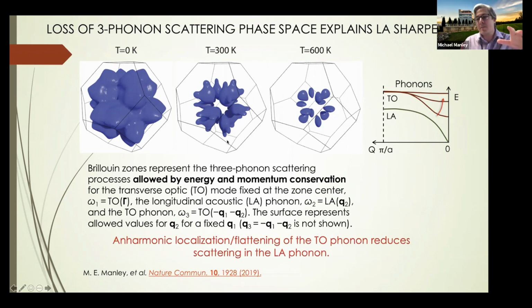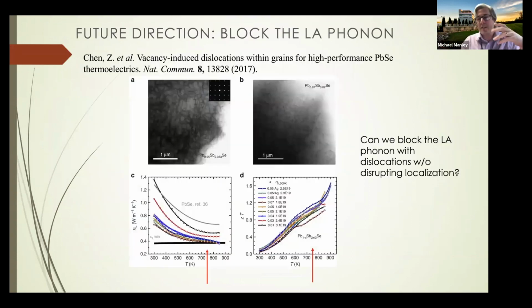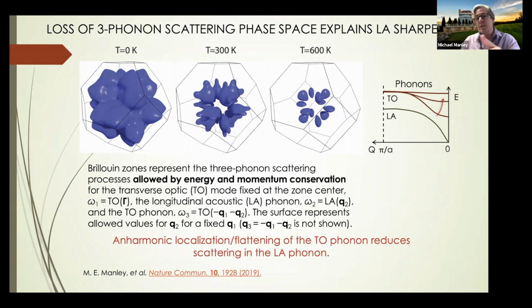So this is a basic problem with the assumption that we often make, which is, oh, phonons become broader at higher temperatures because you populated more of them. But we just assume that the phase space for scattering isn't changing. But when you have a phonon move a lot, you can change the scattering conditions in ways that are very hard to predict because you have a big complicated space of phonons and 3 phonon scattering. What happened is that the localization of one phonon freed up another phonon to travel more easily because it moved something out of the way that it was scattering off, okay?